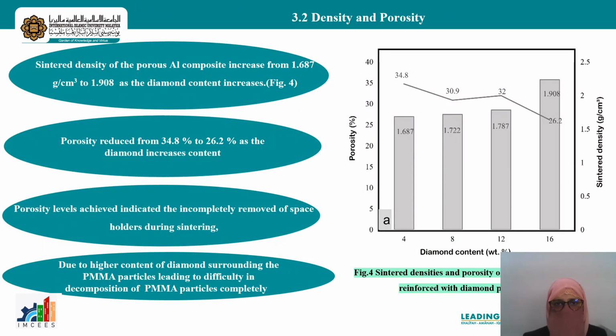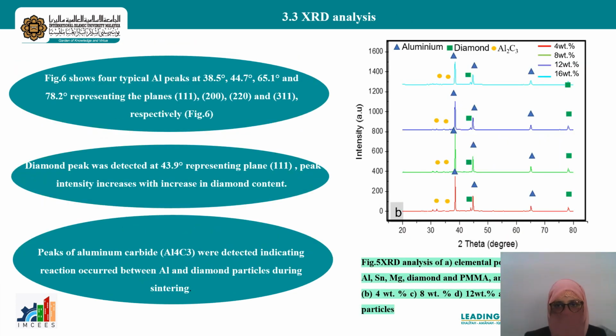Now, the density and the porosity. The density has been seen increasing with increase in diamond percentage, while the porosity decreases. The porosity levels achieved indicate the incomplete removal of space holders, as we only have 30 weight percent of space holders, but the porosity is still 26.2. It means that the higher content of diamond surrounds the PMMA particles and led to difficulty in the decomposition of these particles. Further, from the XRD analysis, we can see the peaks of aluminium and the peaks of the diamond, and also some peaks of aluminium carbide are seen. It indicates that a reaction has occurred between aluminium and diamond particles during the sintering process.